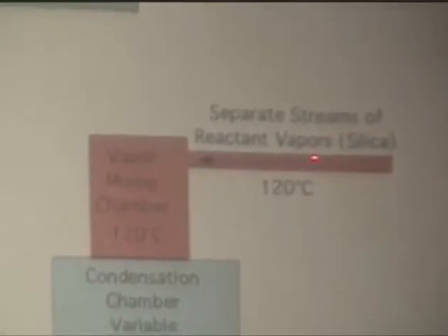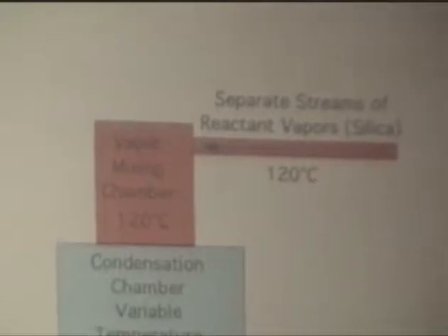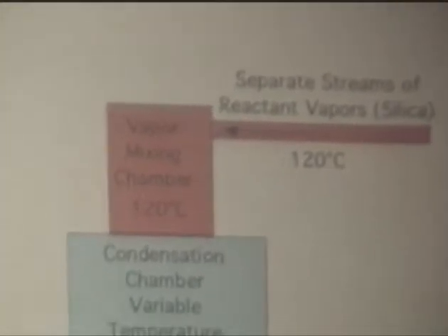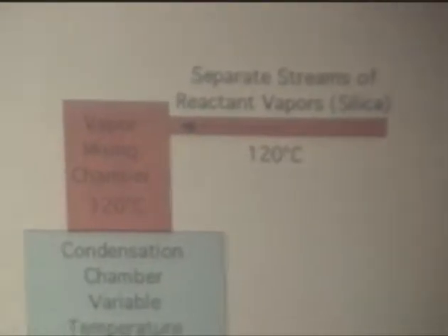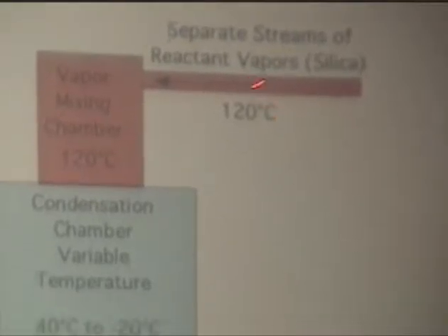One problem is that most silica alkoxides react much slower than titania alkoxides, and this whole picture happens in about 5 seconds as it flows through. Because silica reacts slower, if you co-feed the two components here, you have a tendency to form titania first, and the silica doesn't form until later in the process. So it's possible to feed in silica first, begin its reaction, and then feed in titania at a later point.